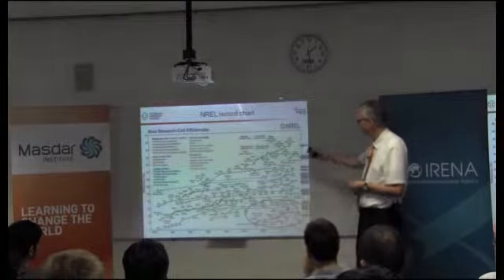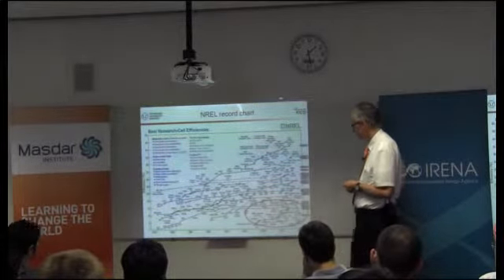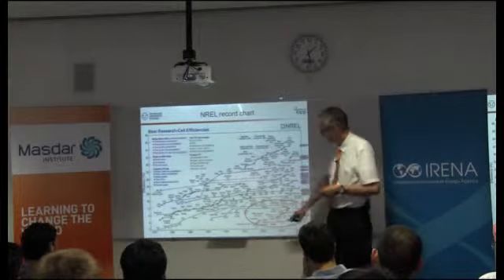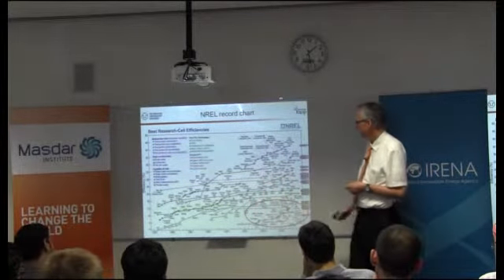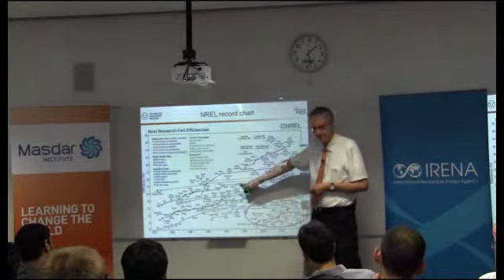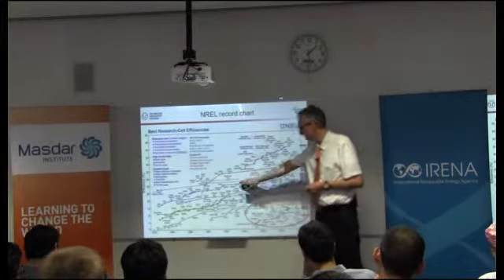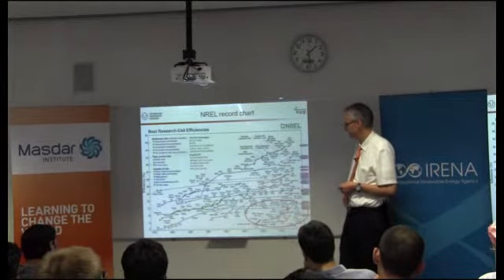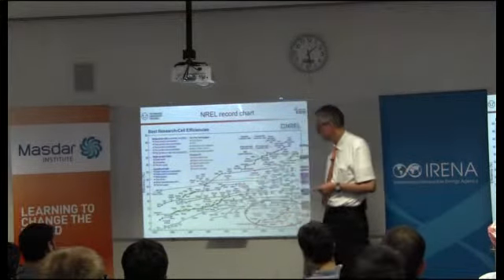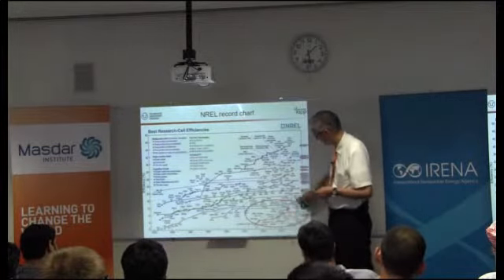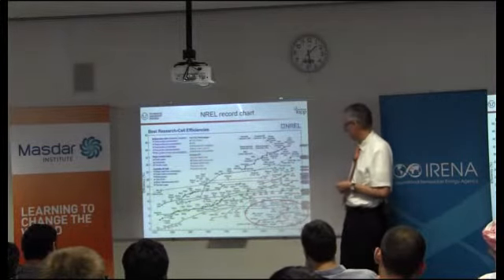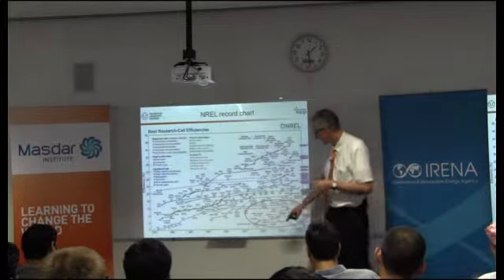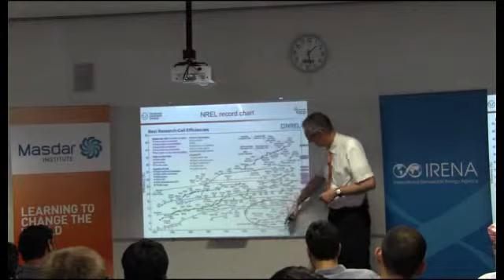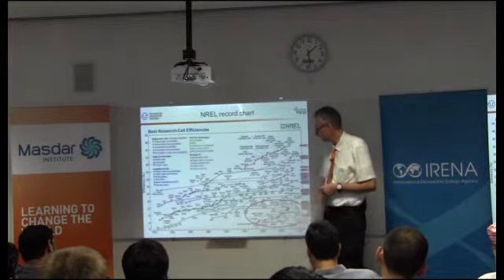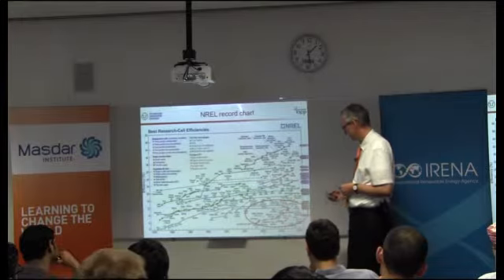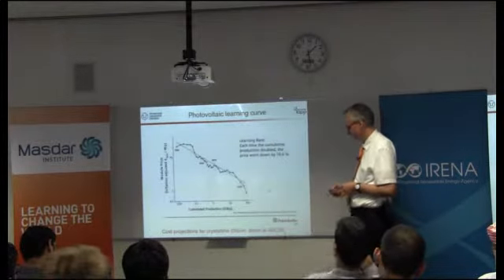However, you know this chart maybe, that's the most important chart in PV. It's actually the efficiency of solar systems versus time. And the most important data point is exactly this one. This is crystalline silicon, University of New South Wales at 25% lab efficiency. And that's the market at the moment. And as you can see, organics is still, I call it, in the noise down there. But the surprising thing, and I'll show it in more detail, is that the gradient, the increase with time, is actually the largest in this field, and that's why I believe that organics is promising. But efficiencies are still low.